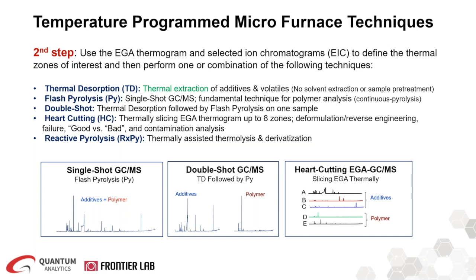The key here is that you are performing a continuous pyrolysis, where the sample is not subjected to heat prior to analysis, as opposed to a pulse mode pyrolysis where the sample is subjected to heat before the analysis starts. You can also do a double shot analysis as shown here, that is performing two analyses on one single sample, thermal desorption followed by flash pyrolysis.